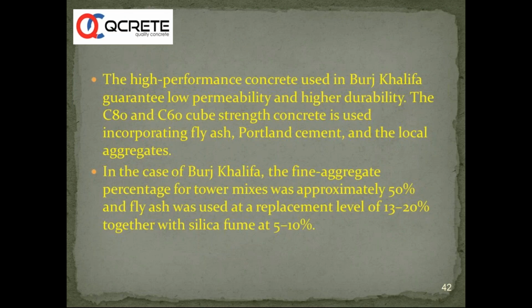So somebody talking about fly ash and hesitant to use fly ash, I request them to think about how they have built Burj Khalifa, the tallest structure in the world. In case of Burj Khalifa, the fine aggregate percentage for tower mixes was approximately 50%, and fly ash was used at a replacement level of 13 to 20%, together with microsilica 5 to 10%. C80, C60, that is M60 and M80 have been done. The tallest building in the world, they have incorporated fly ash. So I don't think we have to be bothered about any other thing actually.